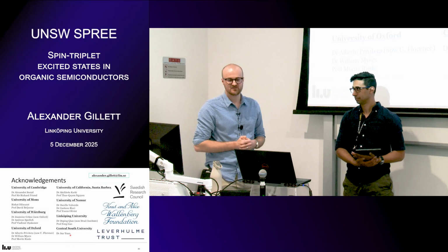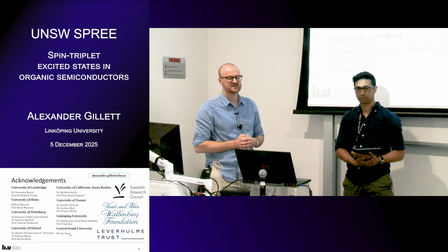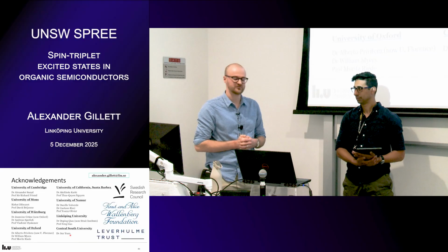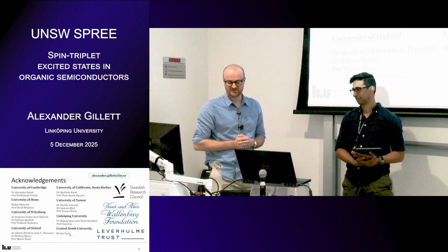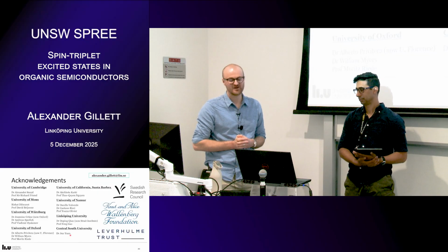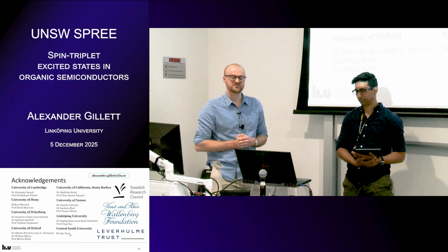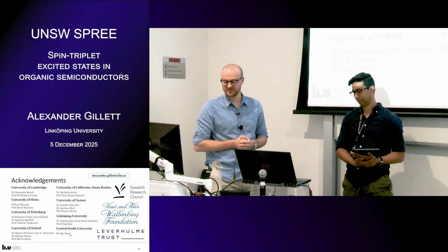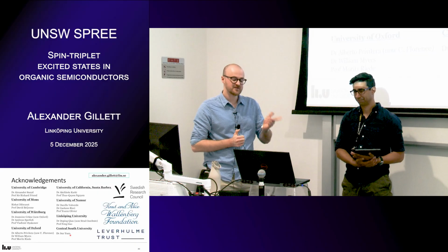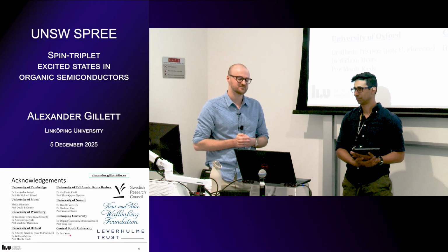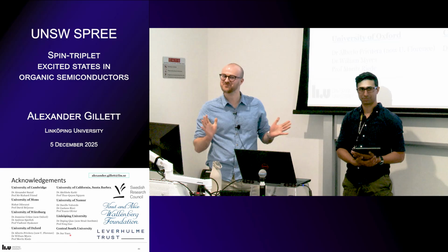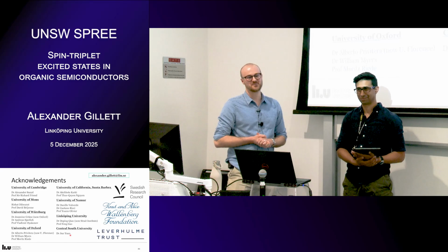So what you just described also applies to a degree to organics, and that's something people are looking into. The problem with making something CT-like is that you win in that way, but it also decreases the radiative rate, which opposes any reduction in the non-radiative rate. So it's quite a careful balancing act, and it also means it doesn't absorb light very strongly, because the oscillator strength goes down, and it's unfortunately no good for an OPV. But it's definitely one tactic, and in the OLED world, where you don't need to absorb light strongly, it's very relevant. For OPVs, maybe other things need to be thought of, which I don't know about. Otherwise, I'd be doing it. So, yeah. Thank you.